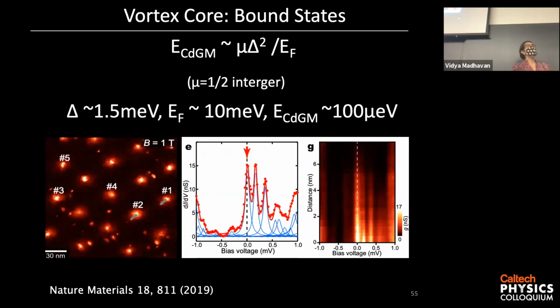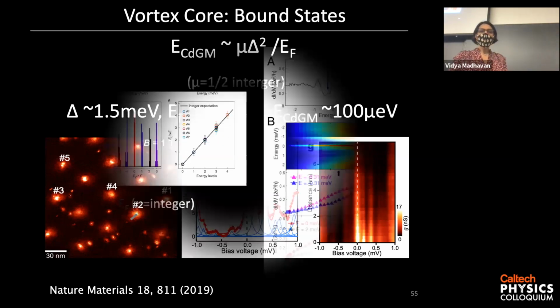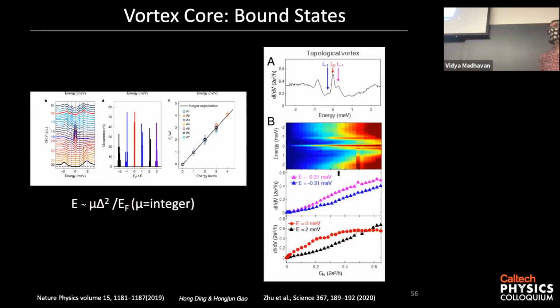So we have another STM person in Japan called Hanaguri, and he did some very nice work, very low temperature STM, 50 millikelvin STM. And he showed that the peak that's at zero bias is at zero to within 20 or 30 microvolts, and very far from where you expect the Caroli-de Gennes state to be. So 100 would be right here. So the zero bias peak that I'm calling Majorana fermion is actually exactly at zero to within the resolution of the system.